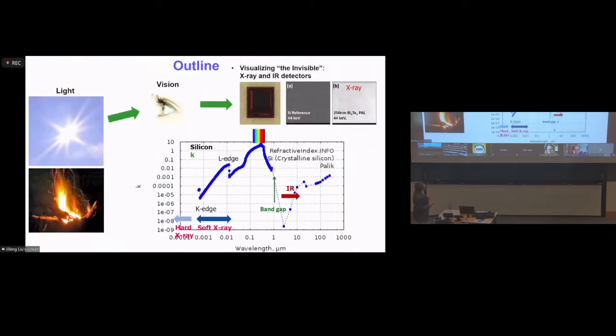So here's a very nice connection to essentially what we were talking about in the first topic. How do you visualize the invisible? We can actually do visible light pretty well with silicon image sensors that you carry in your pocket. That's because if you look at the visible spectrum regime, the absorption of silicon is very strong, near the peak. However, if you go to longer wavelengths below the band gap, the photon doesn't have enough energy to excite the valence electron successfully free to generate free carriers. So essentially, the absorption in the infrared regime is very weak.